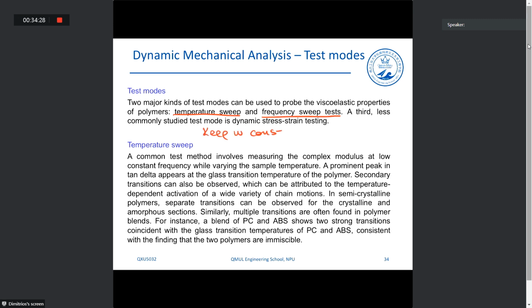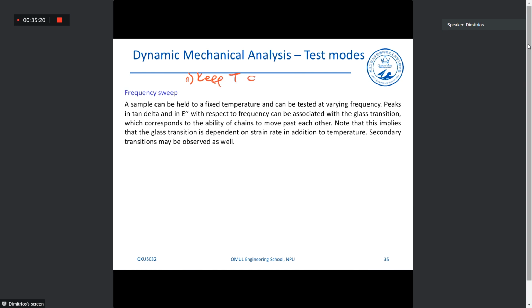It's a measurement method where essentially what we do is we keep the frequency constant, and we ramp the temperature. Usually we use much smaller heating rates than DSC. We use rates from 1 to 5 Celsius degrees per minute in order to have enough time to obtain a good resolution of the tests. And the second mode is a frequency sweep, where essentially what we do is that we keep the temperature constant. Keep T constant. And second, what we do is we variate